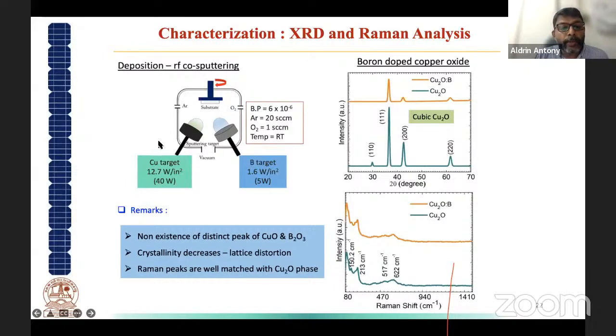So a co-sputtering method was used, and this is the XRD diagram of copper oxide and copper boron oxide. You can see here, this is copper oxide and this is copper boron oxide, with only the same peaks. No additional peaks of boron appear, so the lattice remains the same. It is only a small doping of boron. And the crystallinity actually decreases a little bit, because of the intensity change when you are doping with boron.